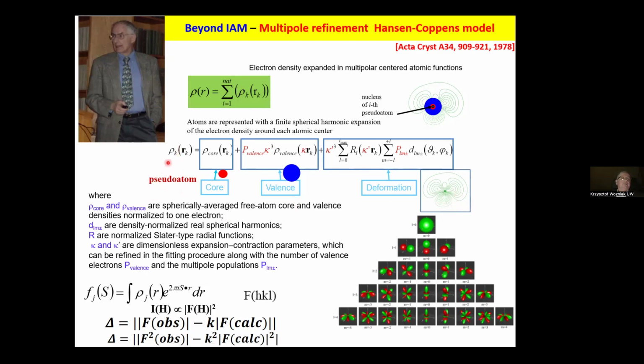Once we've got this atomic electron density, we can Fourier transform it and get a spherical atomic scattering factor. Then we can express structure factors for our model of structure with this atomic scattering factors. And having collected X-ray data, we can minimize differences between those calculated structure factors for our models, between moduli of them, or between intensities obtained for our model and intensity coming from experiments. So by playing with the model, we can minimize those differences. And that's the refinement of electron density.